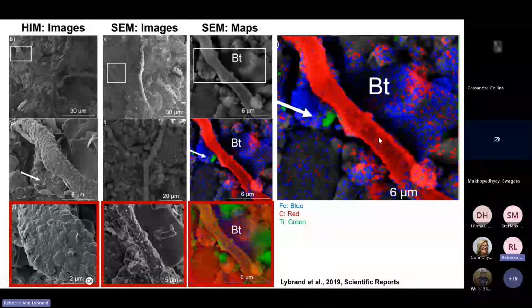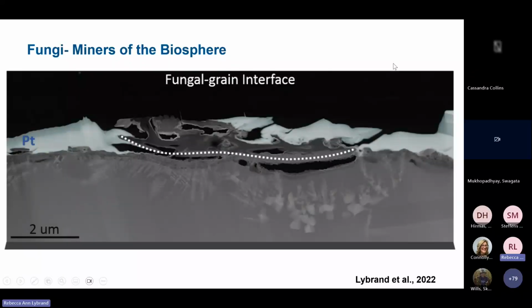Now, we expanded this even more to investigate a fungal grain interface where we also included a focused ion beam, or FIB, to open up a vertical cross-section across a fungal grain interface. And then we also employed transmission electron microscopy to identify what we're looking at with respect to these different types of mineral inclusions. This research expanded to include these techniques, again, at the same exact interface. If you picture this as a vertical cross-section, this is where the fungal growth was, this was the contact with the underlying grain, and you can see this dip here. This is some evidence for direct biological weathering by the fungi, that dip in the grain surface.